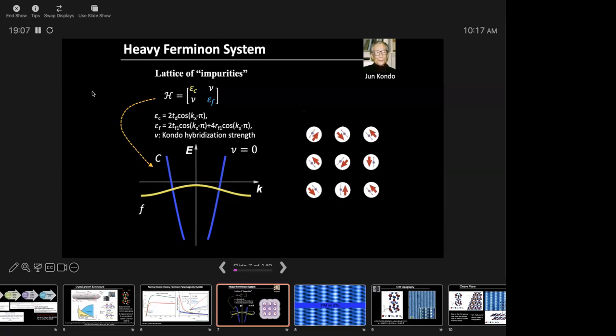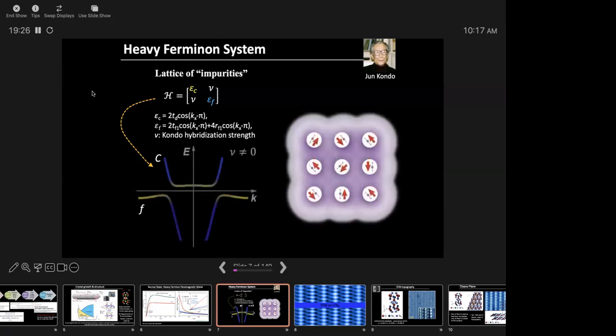And so it's so narrow, you can even think of these spins as localized spins, right? And then what happens in these materials is that there's an interaction between these localized electrons and these conduction electrons. And like in the single impurity Kondo effect, this interaction strength gets larger and larger as you decrease temperatures. And finally, at very low temperatures, you get into this Kondo coherence state. In this coherence state, the localized moments are completely screened. At least if you have a full Kondo effect, you have full screening of the localized moments.